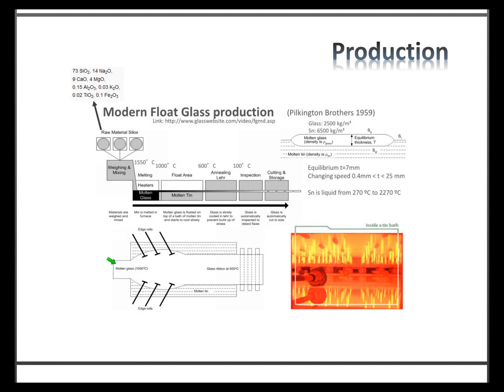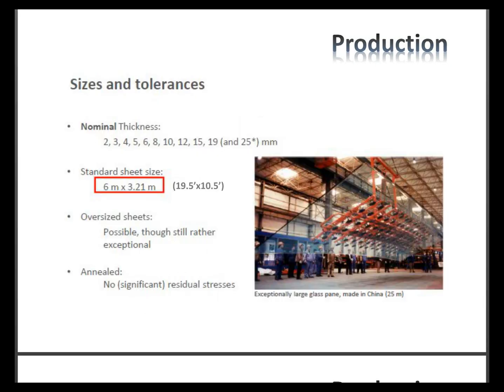After passing through the floating section — where the glass is floated on tin — it travels on rollers through a system where it cools. It is then inspected, cut, and undergoes other processing steps. An important point to highlight: in modern float glass production, the top side of the glass is exposed to air, while the bottom side sits on tin. This can lead to some issues that I will discuss later.